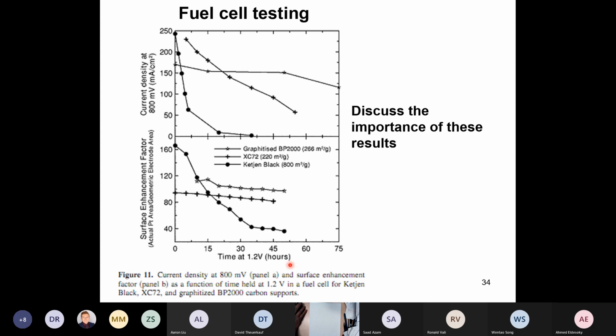So we didn't even talk about the impact of voltage on the rate of corrosion of carbon. We just talked about humidity, temperature, platinum loading, and the graphite, whether it's graphitized or not. So what they're plotting here is at 800 millivolts, how much current can the fuel cell deliver, in milliamps per centimeter squared. For these fuel cells, around 200 to 250 milliamps per centimeter squared was delivered at 800 millivolts. But you can see the fuel cell that used Ketjen Black, 800 meters squared per gram, just dropped like a stone. It didn't take long for this thing to just die.